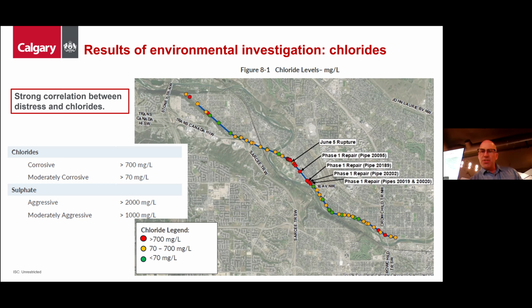With this said, there are some locations with moderate to severe distress pipes with relatively low chlorides and low sulfates. And there are also areas with high chlorides that don't correlate with severe areas of pipe distress. So that's, again, where we're seeing that there are definitely outliers that aren't fitting into the mold that we would expect. There are also locations where the 2014 soil sample showed low chlorides, and then the 2024 samples from the same location show significant chloride levels.